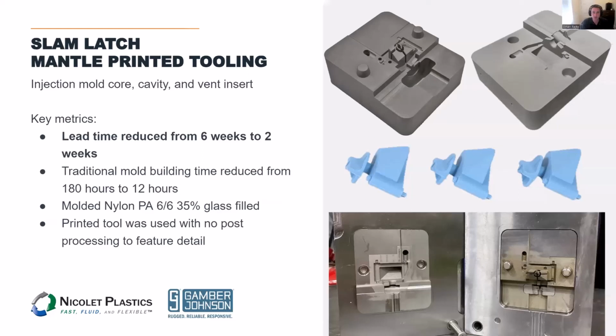So some of the key results here: lead time reduced from 6 weeks down to 2 weeks. The traditional mold building time reduced from 180 hours, they estimated, because of all the sinker EDM work that was required, down to just 12 hours. Molded this 35% glass filled nylon, and then the printed tool was used again with no post-processing to that feature detail that you're seeing up there, which is really, really important. They were fine with that matte finish that you see on this part, and that was totally fine for this actual process.